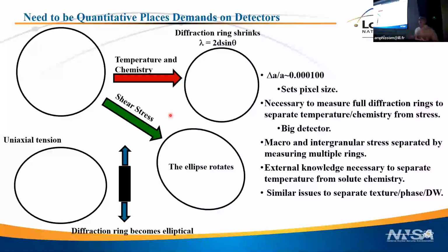Now I need to do that measurement with sufficient accuracy. Typically for mechanical strains, we want an accuracy of about 100 parts per million. That's doable with today's detectors. In order to get the full ring, you have to have a very big detector, at least with X-rays. With neutrons, it's a different thing. So you need a big detector, but you need good enough resolution to get the lattice parameter. In order to separate the intergranular stresses from the macro stresses, you have to look at multiple rings. So your detector has to be big enough to, say, catch 5 full rings. That's kind of what's usually in my head when I design an experiment.